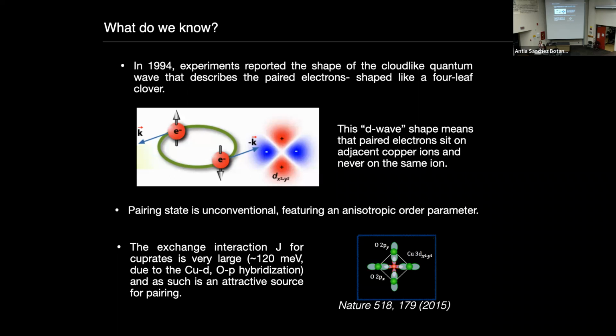One other thing that we know about the cuprates is that we always have strong antiferromagnetic correlations. That's measured by something that we call exchange interaction, and you will see me using this letter J throughout the talk. I may also call it superexchange. And this is for the cuprates very large, somewhere around 120 meV. And the reason why it's large is because in the cuprates, we have a strong degree of hybridization between the copper d and the oxygen p orbitals. And you can see why that's the case in this cartoon, where we have the lobes of the copper d orbitals in red directed towards the p orbitals of the neighboring oxygens that are in green. So as such, this has been perceived as an attractive source for pairing. And even before these experiments, there were already theories that were based on this fact and that had already predicted d-wave pairing as well.